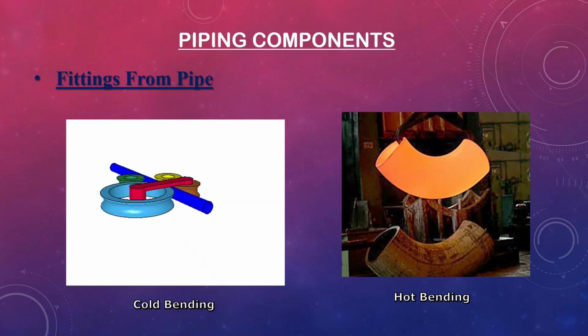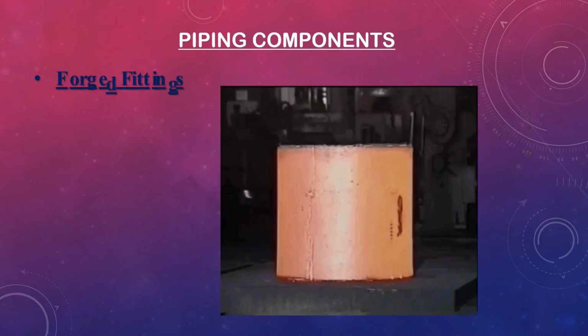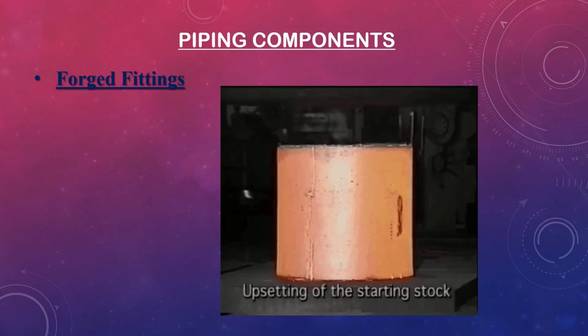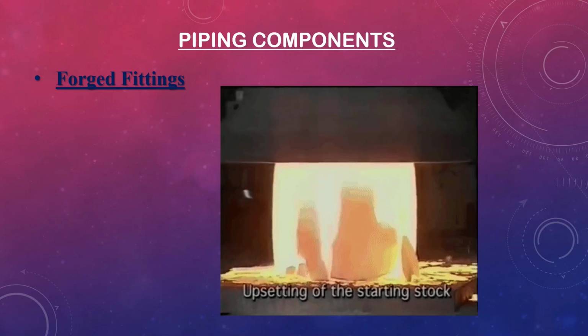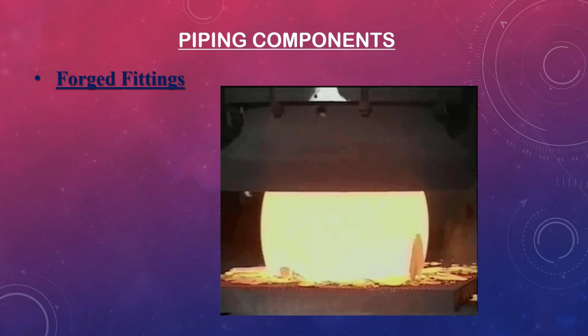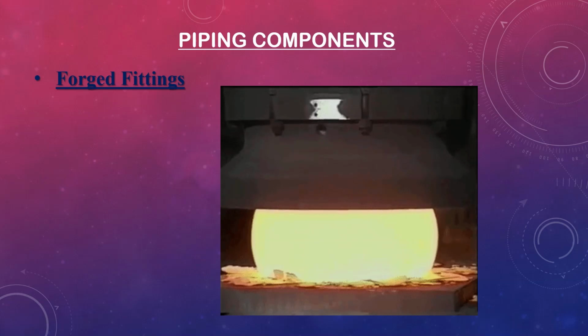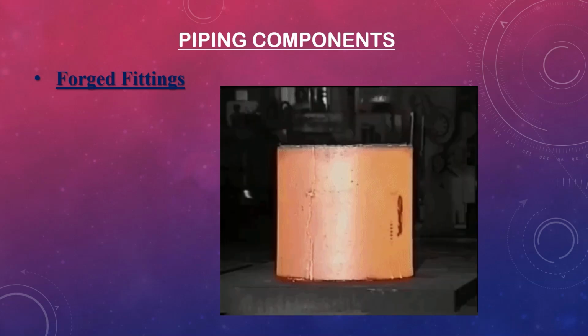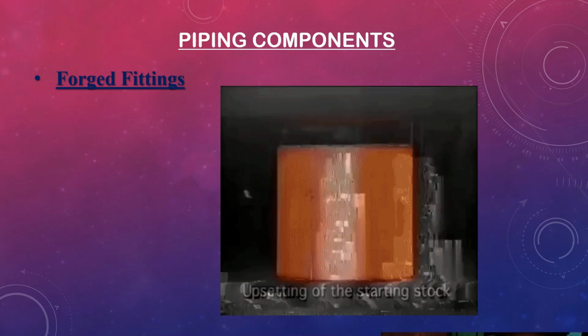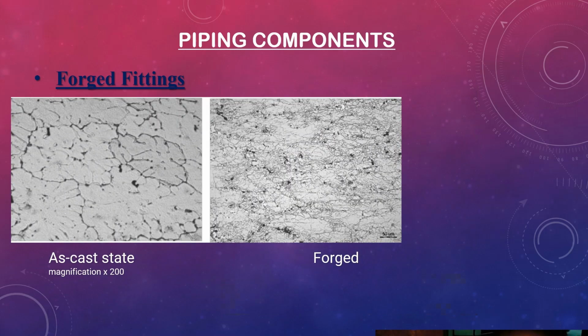But when we talk about elbows, tees, and components that face really intense thermal and mechanical stress, we usually pivot to forging. So why is forging considered the gold standard for high-integrity fittings? Because forging is fundamentally about physical strength through structure. It uses intense pressure hammering or squeezing to achieve what we call plastic deformation of the metal blanks. If you can picture a cheap cast iron skillet versus a finely crafted forged knife, you get the idea. Casting leaves behind microscopic defects like voids or a loose structure. Forging eliminates those as-cast defects, and critically, it optimizes the internal microstructure, aligning the grain of the metal along the stress lines.